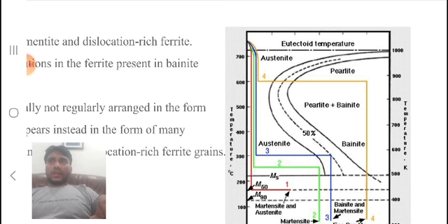The lower carbon alloys have retained austenite at interlath sites, and the higher carbon alloys have zones of retained austenite with their centers partially transformed to martensite, sometimes called massive bainite. Some electron micrographs and schematics of these structures are shown in the figure, and respective hardness data, engineering stress and strain, and ductile-brittle transition temperature plots can be easily plotted.